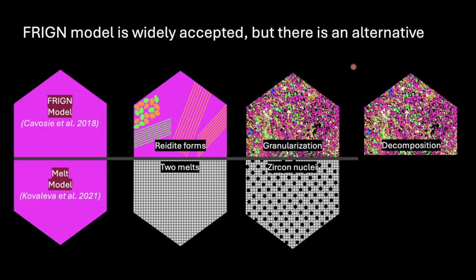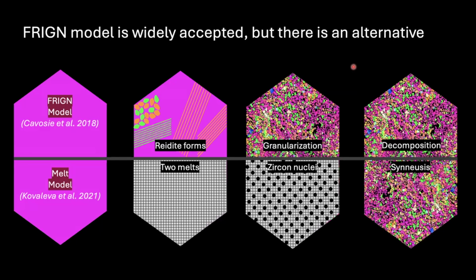Then it's very undercooled and you get zircon nuclei that are forming out of the melts. And then eventually those grow and they spin and they only connect with each other and adhere when they have minimized surface energy. And that relationship, the mutually orthogonal relationship, is expected to minimize surface energy. So by her mechanism, she says you can make this without ever making Reidite.